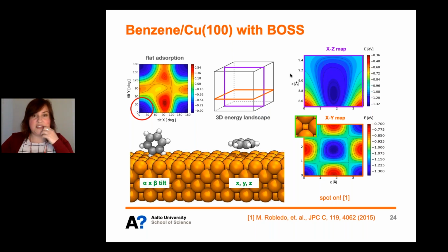Now, this system has been simulated before, a few years ago, and what they did is the traditional way, where they just looked at 3 possible sites, and they relaxed all degrees of freedom. And we were very glad to see that our energy scales reproduced spot on those results, even though we did no relaxation here. This is just because the building block approximation is so good here.